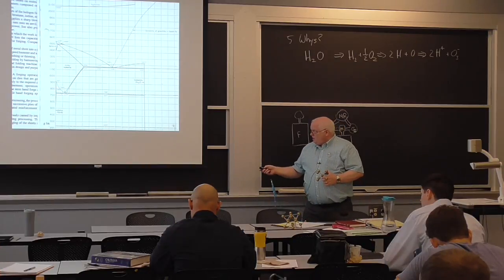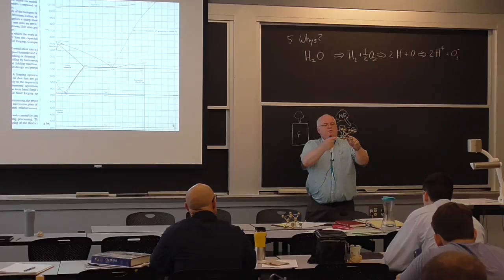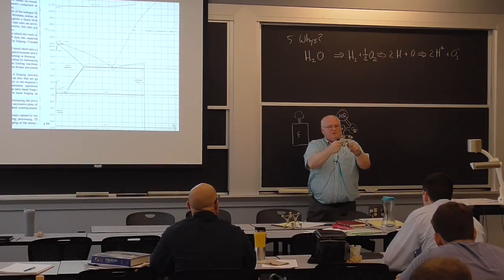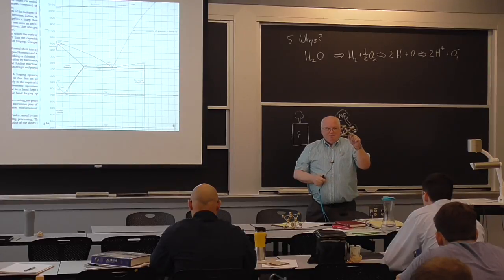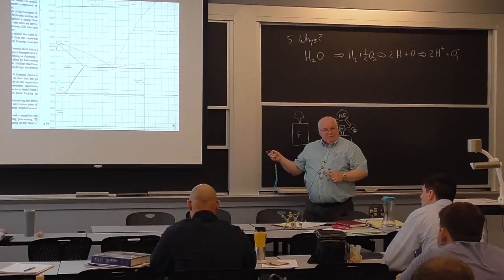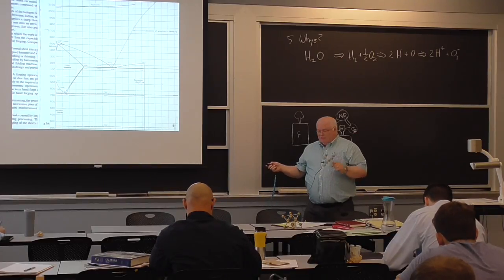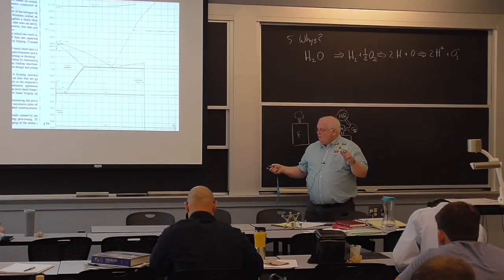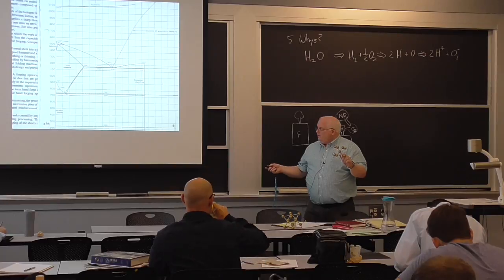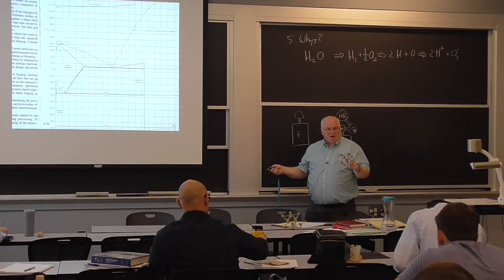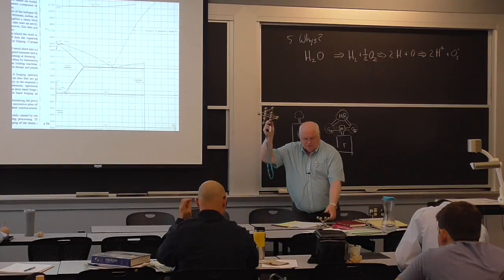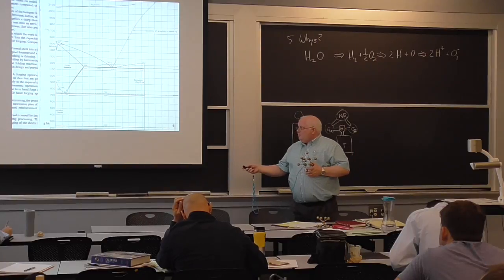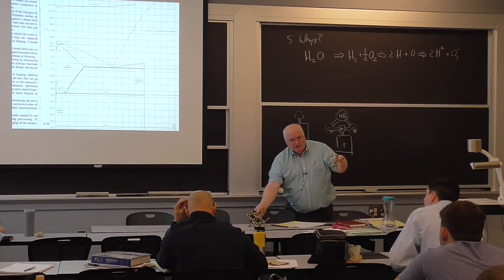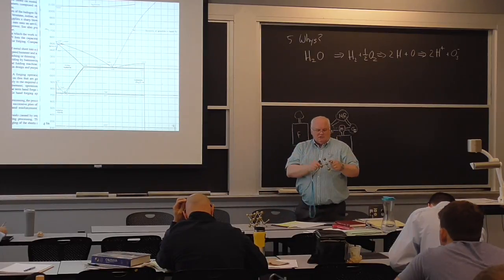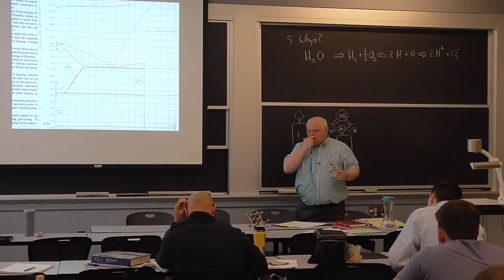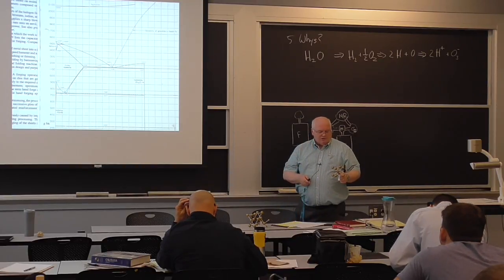At low temperatures, the stable form of iron is body-centered cubic, which you got a cube, but instead of an atom on each face, each one of the 6 faces, you got one in the center. Okay? That's BCC. So you have FCC, or gamma, or austenite. Down here you have alpha iron, or BCC, or what we call ferrite. But when you quench this stuff from the high temperature and cool it very rapidly, you won't get exactly this. You'll get another phase, which comes out as little needles. It's called martensite, after Adolf Martens, who was a metallurgist in the late 19th century.